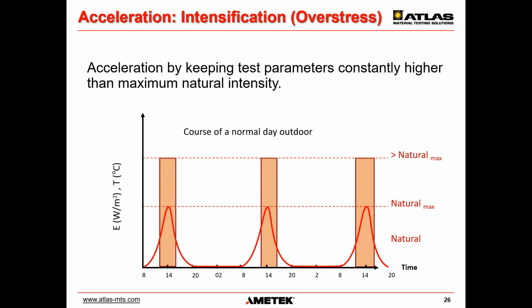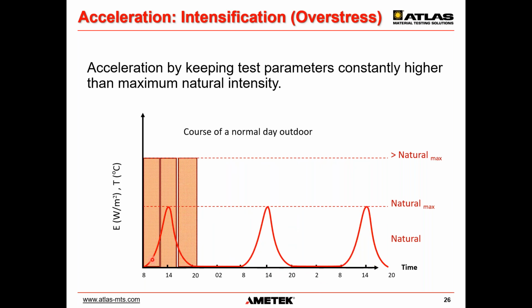Of course, it is also possible to accelerate both through time compression as well as through overstress. Of course, you eliminate nights and dark times, and you overstress, and then you get even more acceleration. Modern xenon arc instruments and also fluorescent UV devices do have the ability, and various test methods take advantage of that, and allow irradiance higher than maximum irradiance, usually up to 3 sun level, which is 180 watts per square meter in the UV between 300 and 400 nanometers.